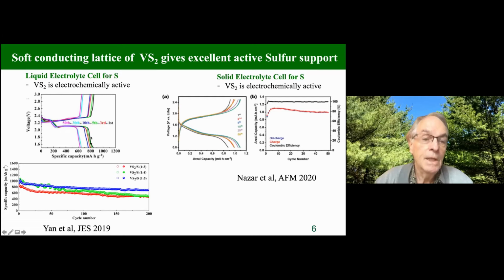And you can see with this, you're getting about 800 milliamp hours per gram with a liquid electrolyte. And Linda has shown that with a solid electrolyte, you can also cycle this material with very good coulombic efficiency and capacity retention. So these layered sulfides are outstanding cathode materials, with one exception: their voltage is too low. Their big advantage is the metallic conductivity.